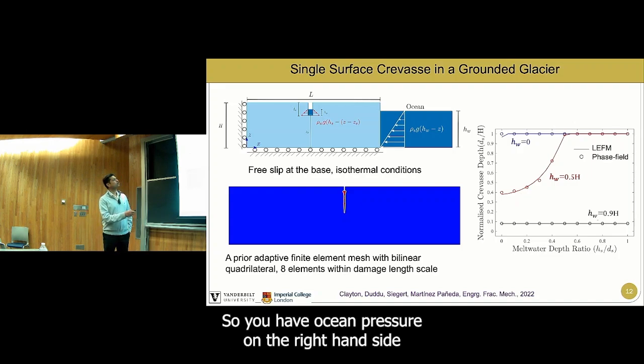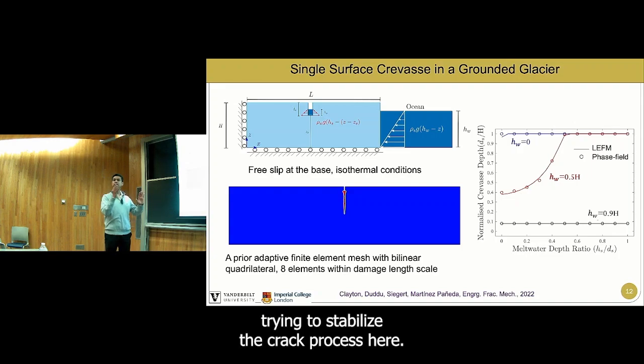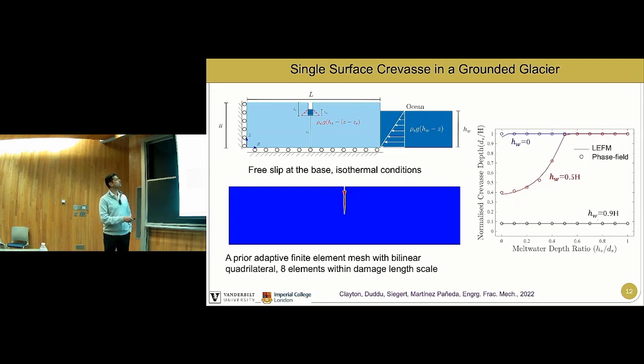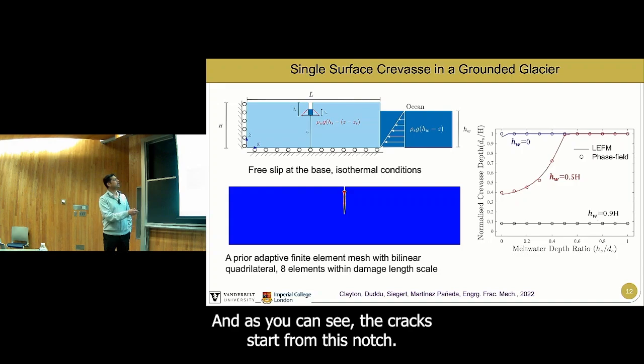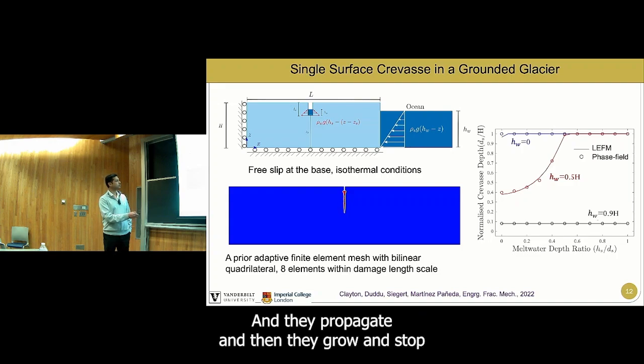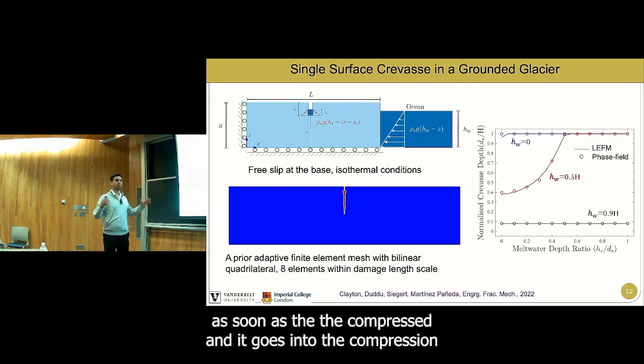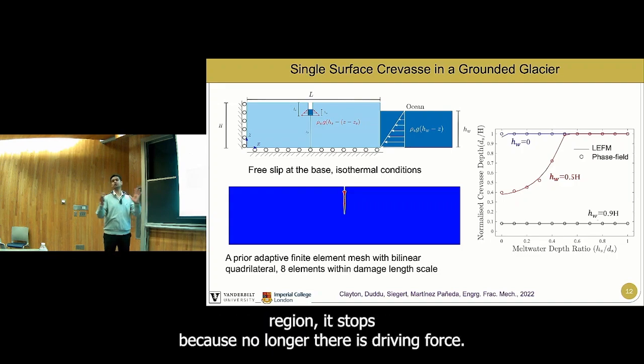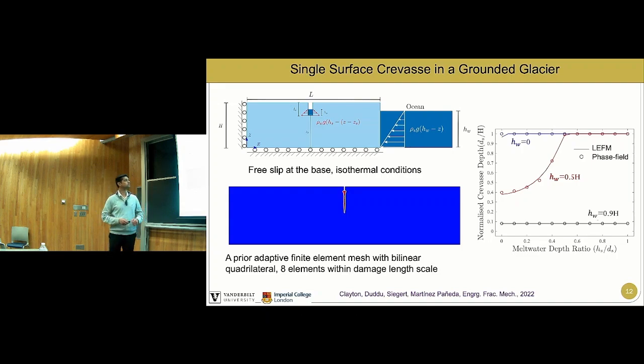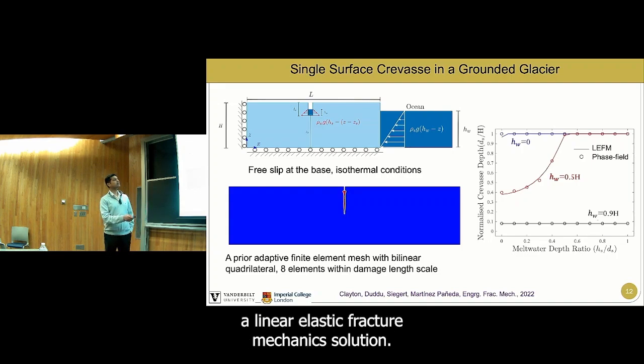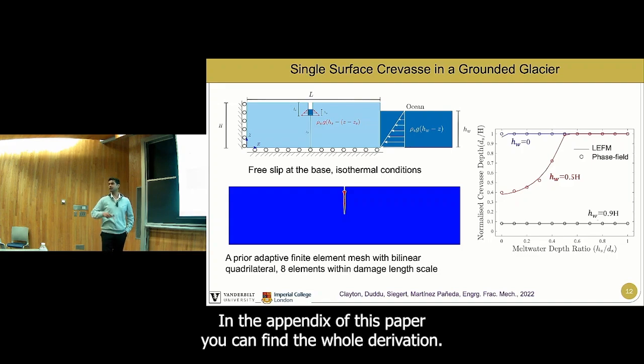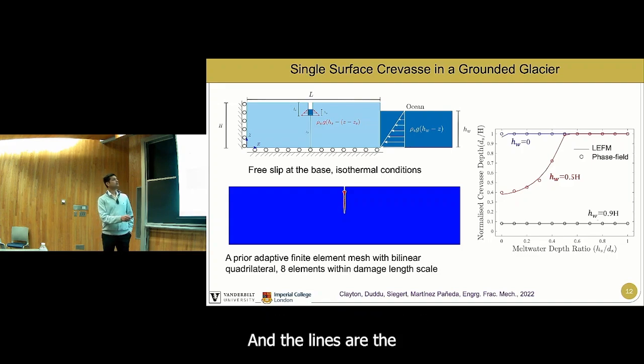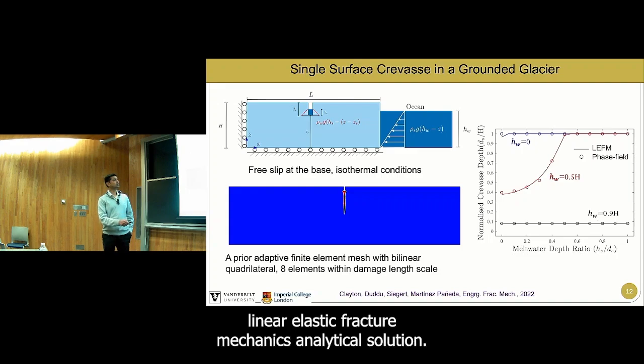So you have ocean pressure on the right-hand side trying to stabilize the crack process here. And as you can see, the cracks start from this notch and they propagate and then they grow and stop. As soon as it goes into the compression region, it stops because no longer there is driving force. And then we derived a linear elastic fracture mechanics solution. In the appendix of this paper, you can find the whole derivation. And the lines are the linear elastic fracture mechanics analytical solution.